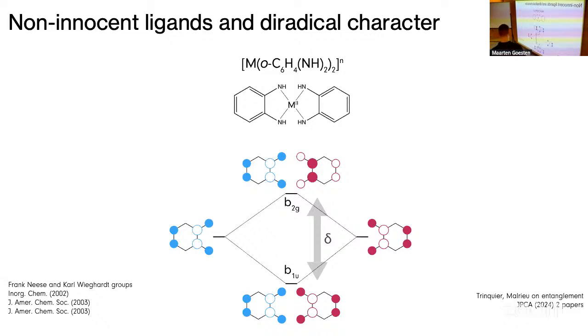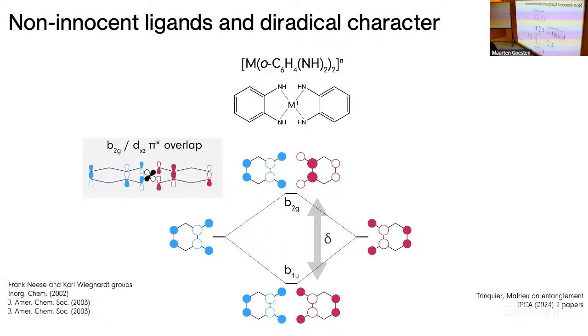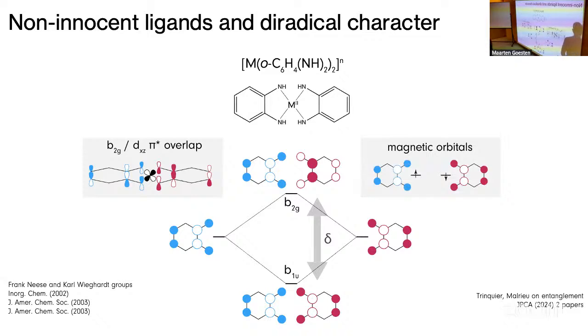What happens here, and remember the irreducible representations, is that we have these two interacting ligands interacting with a divalent metal. We get a small gap opening up between the B1U and the B2G irreducible representations. That gap is predominantly controlled by an antibonding interaction with a metal d orbital. That is happening only for this representation here, and that lifts up the level. If you just do DFT, single particle molecular orbital theory, you just put these two electrons in the B1U level, right? But in the real situation, a degree of diradical character mixes in. So this is a case of what in physics is called strong correlation, in chemistry, static correlation.